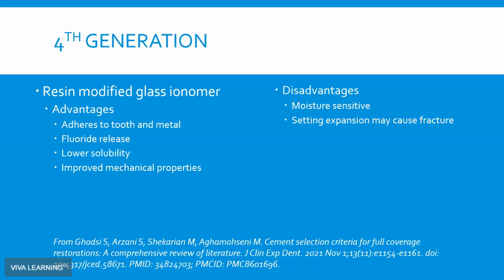And indeed, when we've had crowns, either 10, 15 years later, either debond or more likely when removing a tooth, let's say, or some other fracture, it is interesting to see, especially with modern prep designs, meaning a chamfer type or a butt margin type of preparation on an all ceramic restoration, at least in my experience, the kind of microleakage and all the black scuzz. For the subgingival margins anyway. Supragingival seem to be okay, but obviously fairly unaesthetic in many areas.